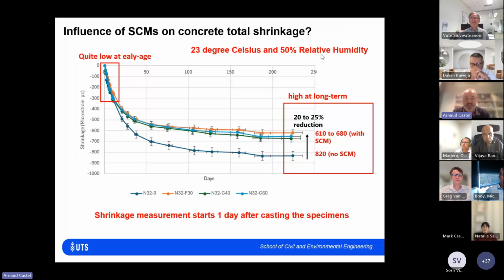So I'll start to talk about test results from the CRC project, where we try to look at different concrete here. So we have a 32 MPa concrete. There's several of them. There's the 0, which is no SCM, then 30% fly ash, 40% slag, 60% slag, and we see how the SCM content is influencing shrinkage.